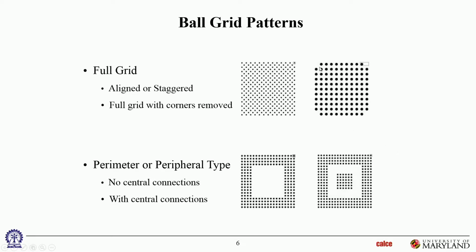So just as I want to add some input to here, yeah, the failure rates, if you compare the corner ones and the inner corner ones. Mhm. So if you see the corner ones, it will be only in the corners. It's like a triangle. Right. The failure will be in the four corners. But if you take the inside, the square, it will be the whole row and the column. Right, right. So there it gets muted, and that's because of the underfill. The diagonal, the length effect gets muted a little bit. So all around the edges, it'll fail. Yeah, good point. We like that. Can the center square be tilted by 90 degrees or something to cancel out the